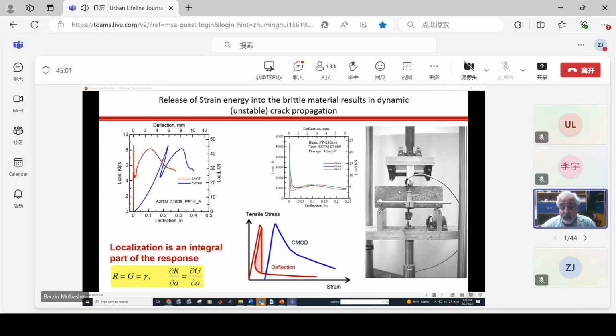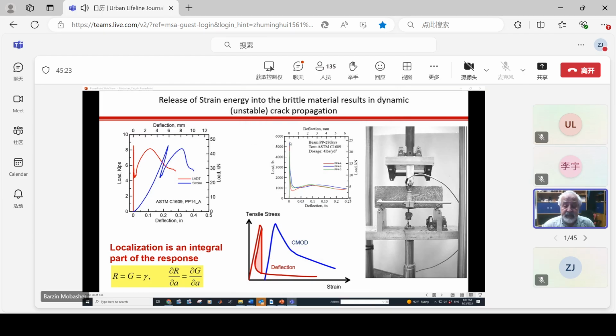What am I saying? What I'm saying is that when you load a specimen in flexure, there is so much energy stored in it that the moment the crack initiates, if it doesn't have a lot of fiber or has a very small amount of fiber, the energy stored in the specimen is enough to cause the fracture of the sample. So many times we run into a test like this. The sample goes up, it hits a peak, but then immediately the load drops. This is not the full response of the specimen. This is because the material is so stiff that it cannot give the energy back to the test machine. It gives the energy back to the test sample. And that's what we call snapback, meaning that the load decreases as the deformation decreases, and then it starts picking up and going there.